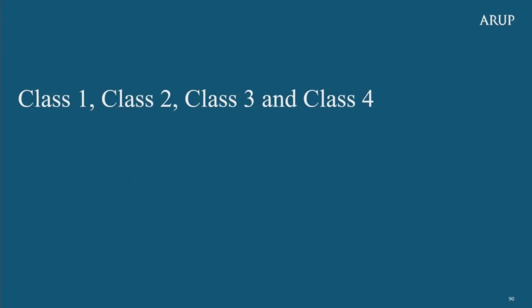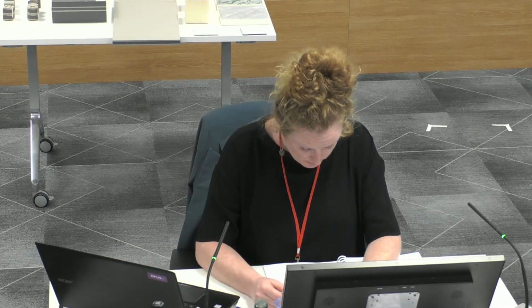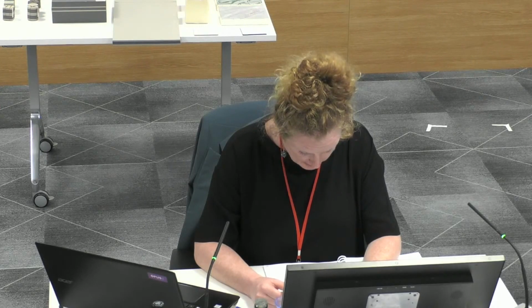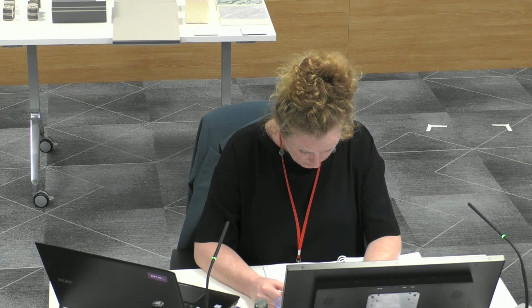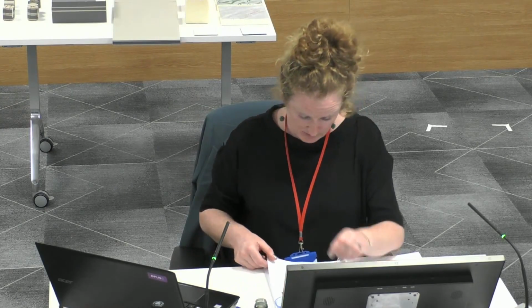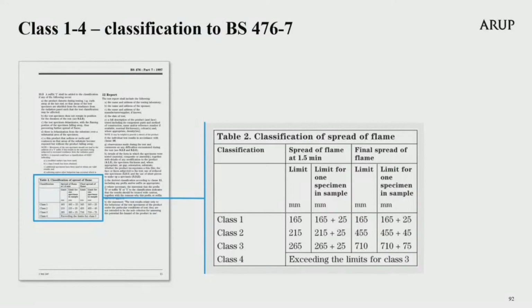I want to now explain how Approved Document B refers to the classes 1, 2, 3 and 4, as calculated in the Part 7 surface spread of flame test. Classes 1 to 4 are surface spread of flame classifications, and these are defined within Part 7 itself. It's not referred to again in Approved Document B. The resultant class is simply a measure of how far along the specimen the flame spreads horizontally over 2 time steps. Of the 4 classes, class 1 is the highest and 4 is the lowest.